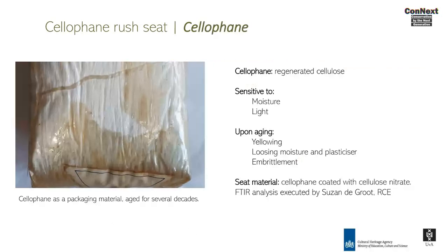So what is cellophane actually? Cellophane is a transparent film material that has mostly been used as a food, flower or cigarette packaging material. It's increasingly used again because it's biodegradable. Cellophane, namely, is not a plastic. It was patented in 1912. To make cellophane, cellulose from plant material such as cotton is dissolved to make it viscous. It's then extruded through a slit die into an acidic bath where it's converted into cellulose, now in the shape of a film. Then it can be bleached or plasticized.